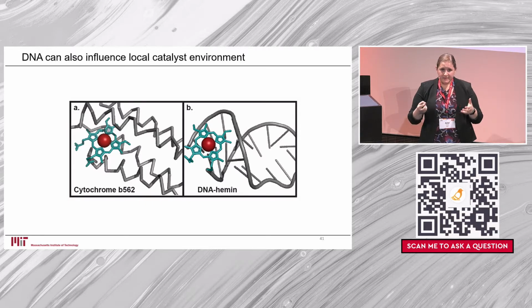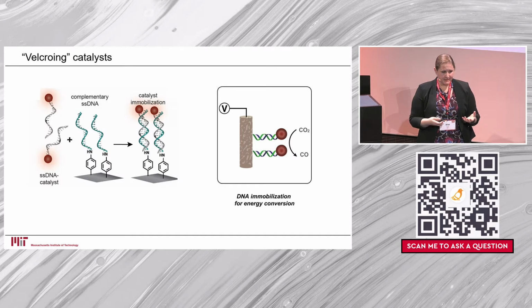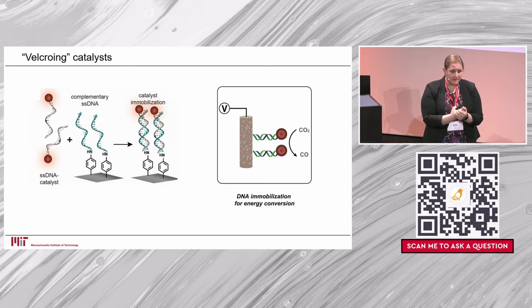So we thought that using this DNA would not only allow us to specifically place these catalysts, but also improve their local environment. And so what I'm going to show you now is some data where we were able to modify one strand of DNA with the catalyst. We can modify an electrode with the complement. And when we mix those two solutions, that catalyst naturally hybridizes to our surface with about 98% efficiency.